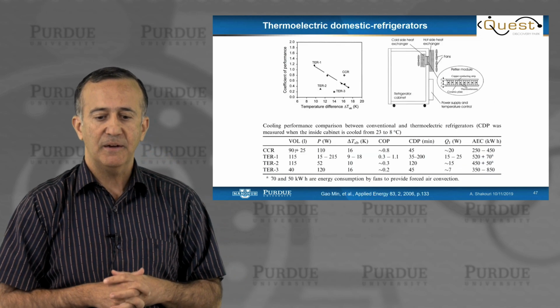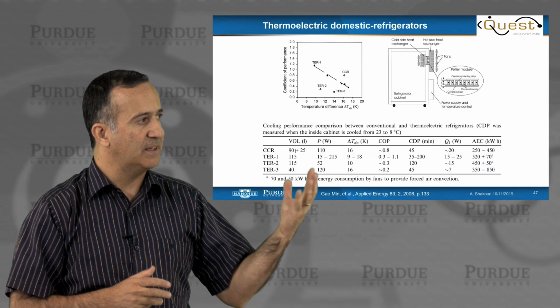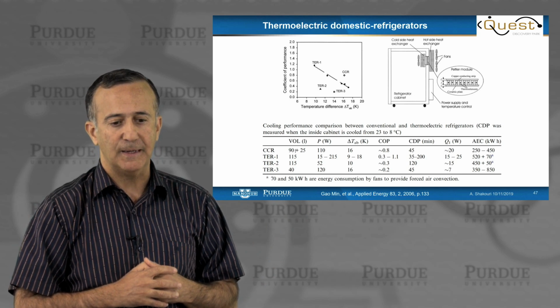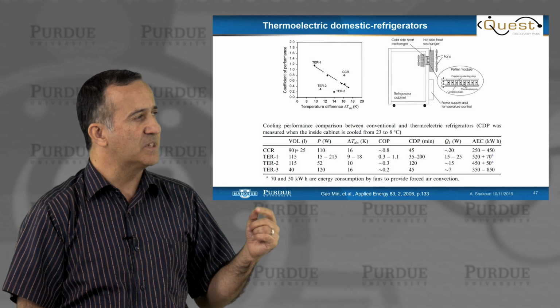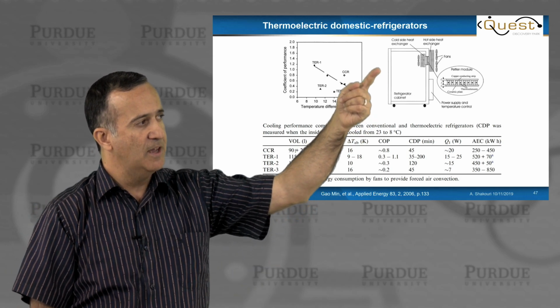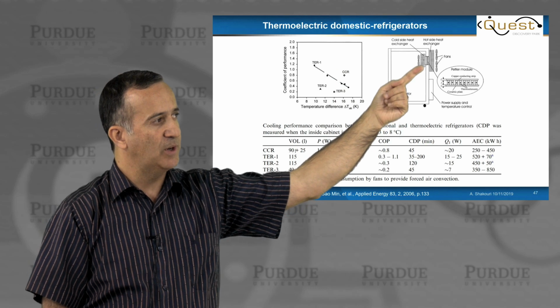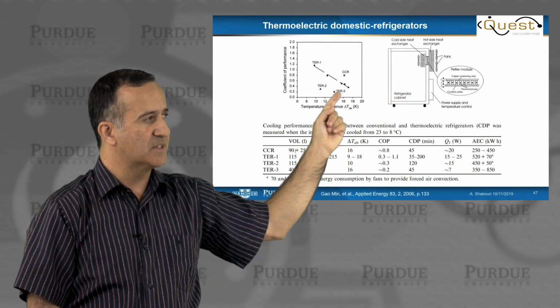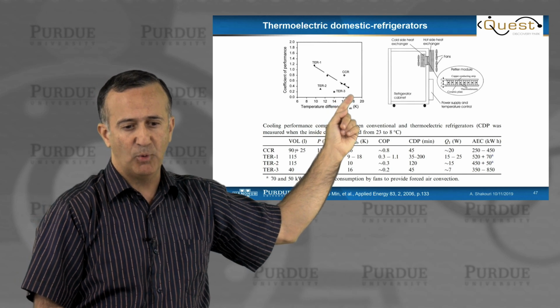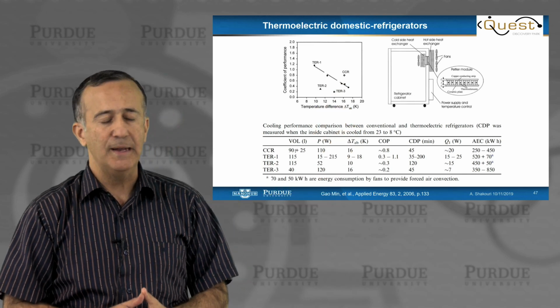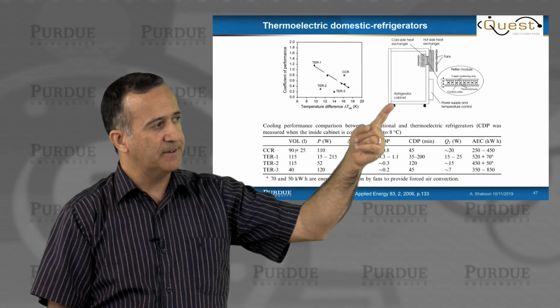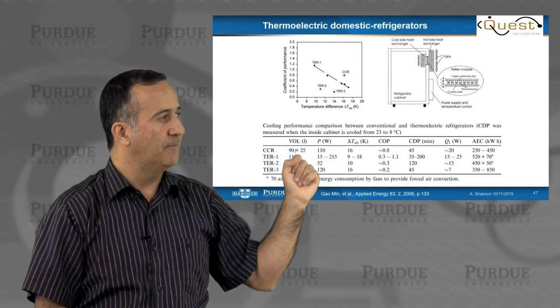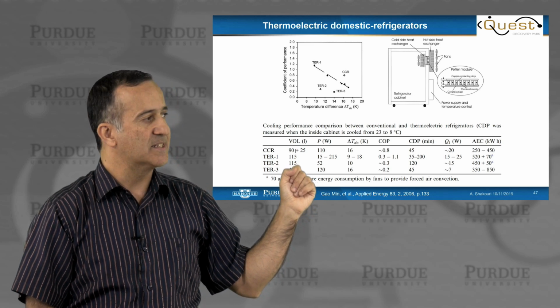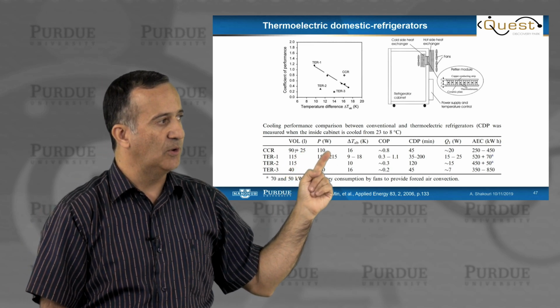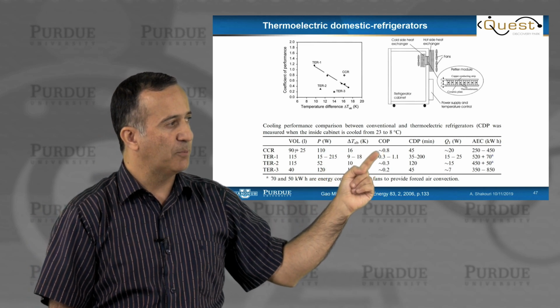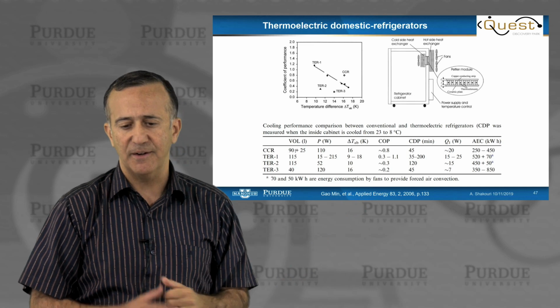So here was an interesting paper that compared the performance of thermoelectrics for a small scale refrigerator. So it's a case where you have a casing and just a thermoelectric module. The COPs are small, about 0.2 to at most about 1. For the small size refrigerators, because mechanical engines don't scale as well, the COP is also low, but still, you see it's about 0.8. So this is a case for small scale refrigerators.